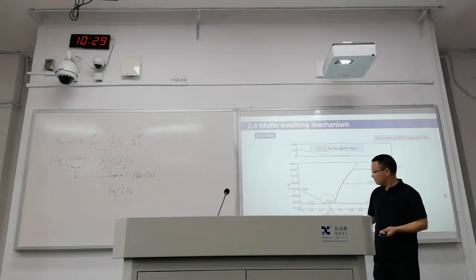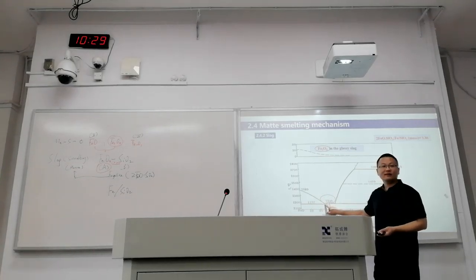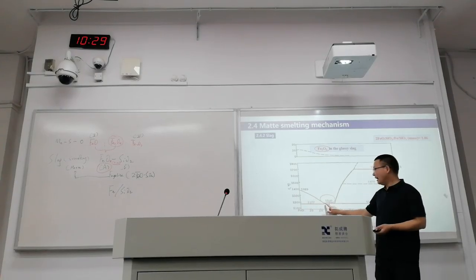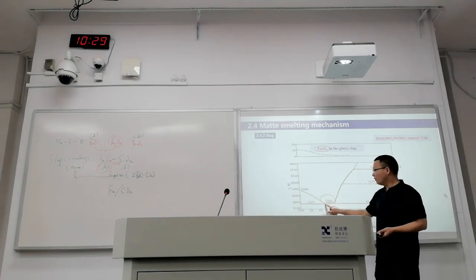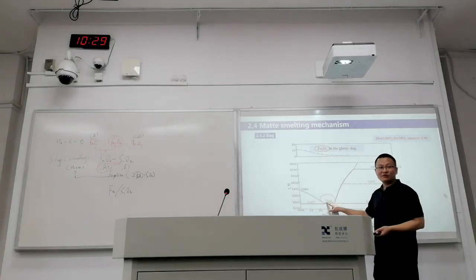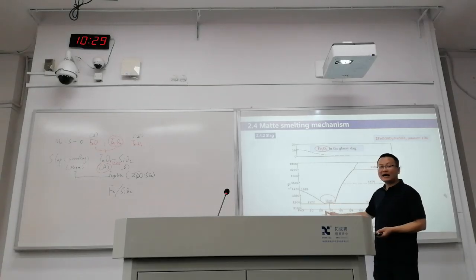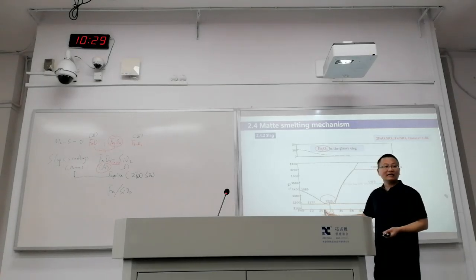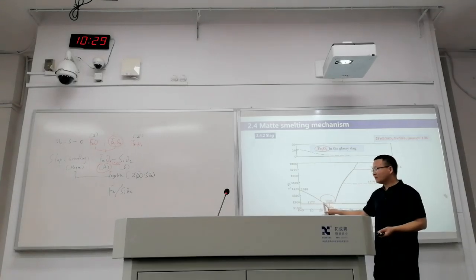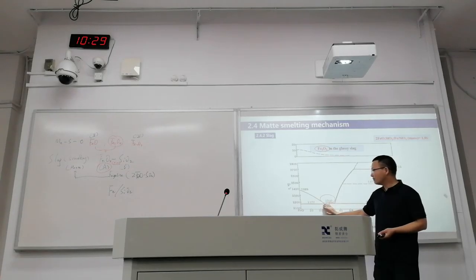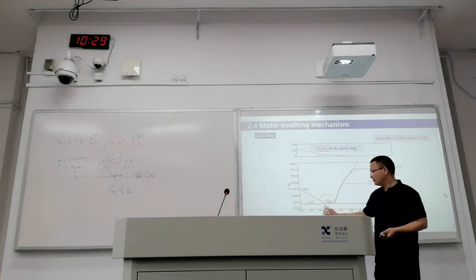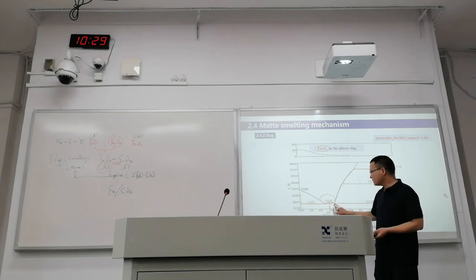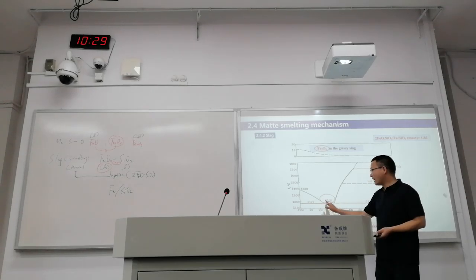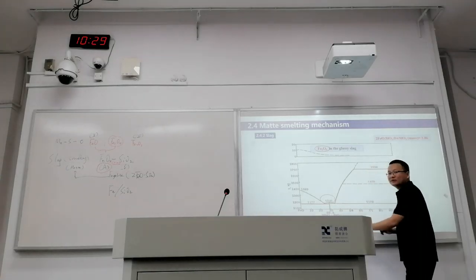So theoretically, this one will be an ideal one: lowest temperature before the increase of temperature, and we have a reasonable iron to silicon ratio, right? This is an ideal point. But the reality is that we are not making our production at this point. We are moving to this side, which means we have to add more silicon oxide.